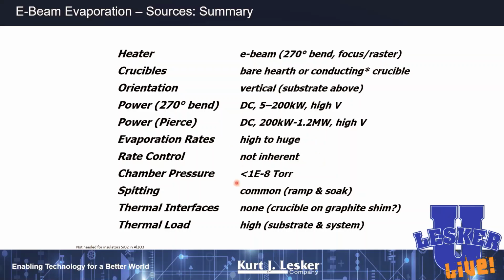Again, I want you to go to the lowest possible pressure you can achieve in your system. And again, you get to the lowest numbers when the system is clean. So please try to keep your systems really, really clean. And again, your thermal load now on your substrates is really, really high. And so if you're trying to do film through PMMA, or if you're trying to use organic substrates like cellulose, you've got to be really, really mindful of the temperatures you're going to get to.